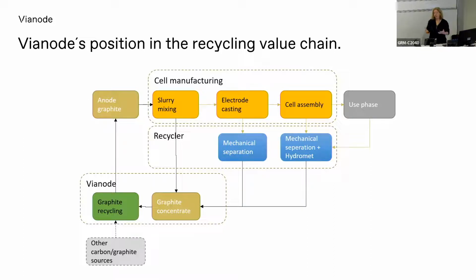So somewhere between 20 and 30% of the material that we sell to our customers every year ends up just going out the back door of the plant into the trash, which is not very sustainable. And so we have started to do a lot of work with them on how we can recover that material instead of just throwing it away, turning it back into graphite material that they could feed directly back into their process, which saves them money. It's good for the economy. It's good for sustainability. Overall, good for everyone. And so we work with companies that do recycling on mechanical separation of the materials and also hydrometallurgical processing of the materials in order to recover the graphite and turn it back into the usable graphite material.